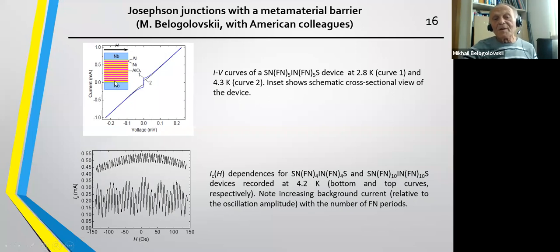Therefore, we have strong scattering, and if we are speaking about the central part of the junction, in this case, we have some trajectories to the left of this part and trajectories to the right part. They can cancel each other. And the result in the center is that there is no supercurrent, or it is of a very low value. Another situation is near the edge, since near the edge you have only trajectories from the right side here and from the left side. So there is no such compensation as in the center. And the strongest situation is near the hinge, when the current is one-dimensional.